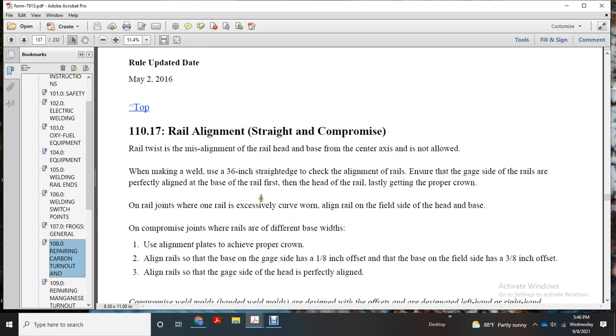On rail joints where one rail is excessively curved or worn, align the rail on the field side of the head and base. This is the compromised joint, where rails have a different base width. Use the alignment plate to achieve the proper crown, aligning the rail's base on the gauge side with a 1/8 inch offset, and the base on the field side with a 3/8 inch offset. Align rails so the gauge side of the head is perfectly aligned.